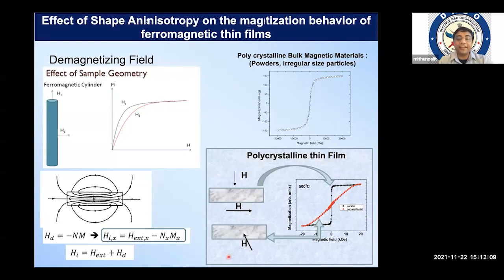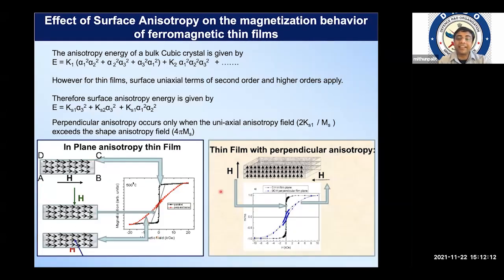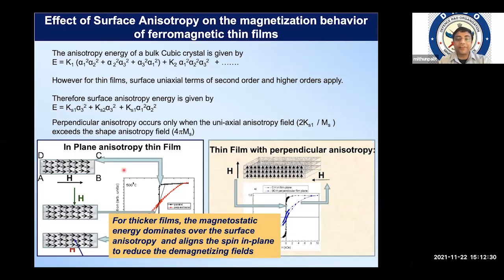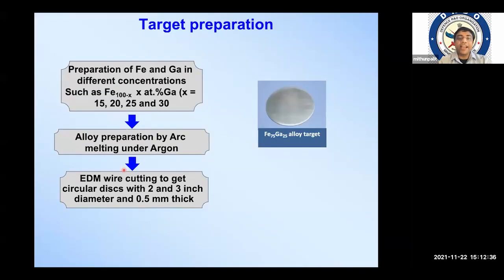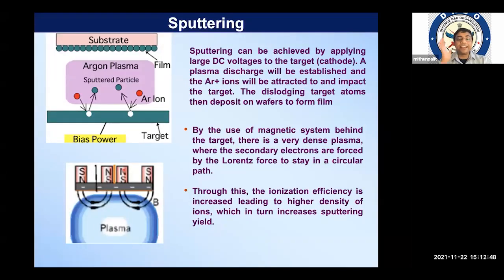And there are other factors, like thin film thickness, which is another important thing. Whenever the thickness is thin, the magnetic domains align like this. That is called the perpendicular anisotropy. And when the thickness is more, the magnetic domains align along the plane. That is called the in-plane anisotropy. So therefore, surface versus volume plays an important role in the case of thin film. We prepared this magnetic thin film first through the sputtering technique, and to do so, we first had to prepare the target. We prepared the target in-house, and then using the sputtering technique we prepared this magnetic thin film.